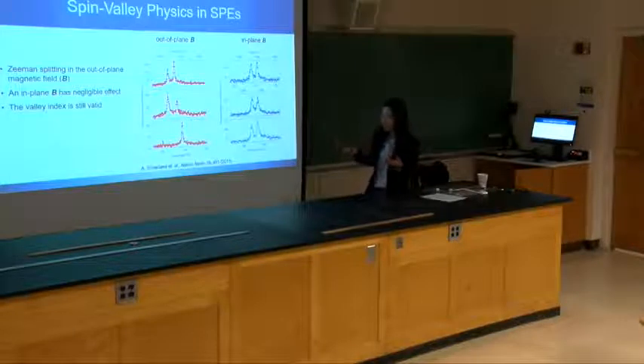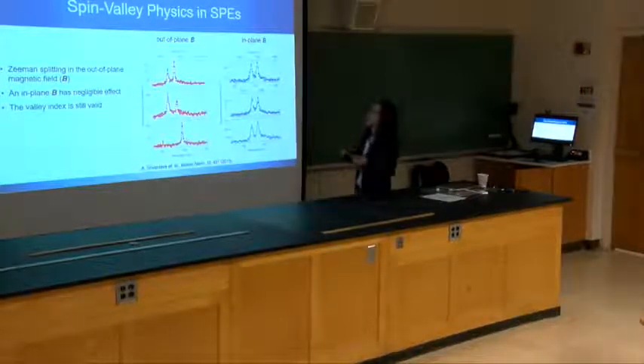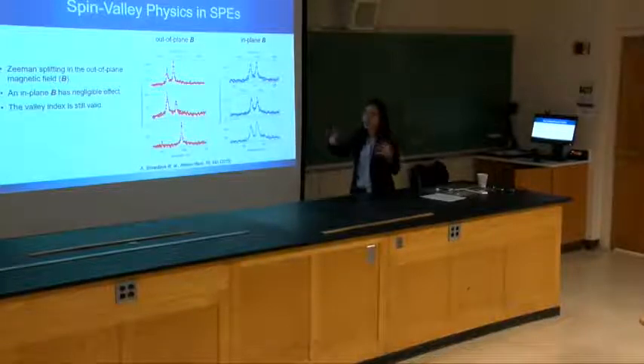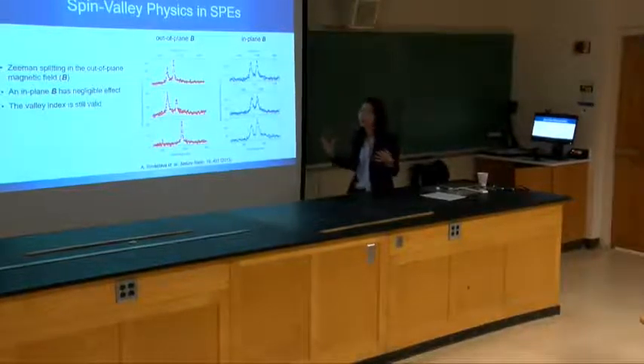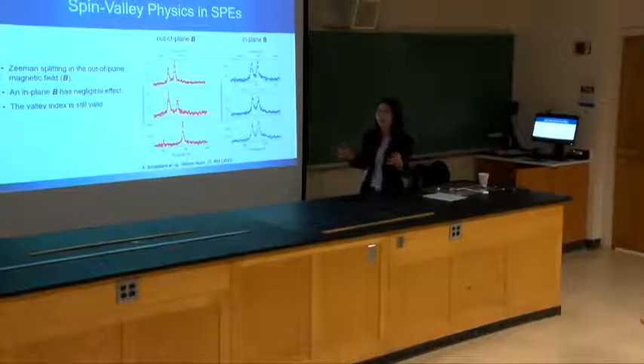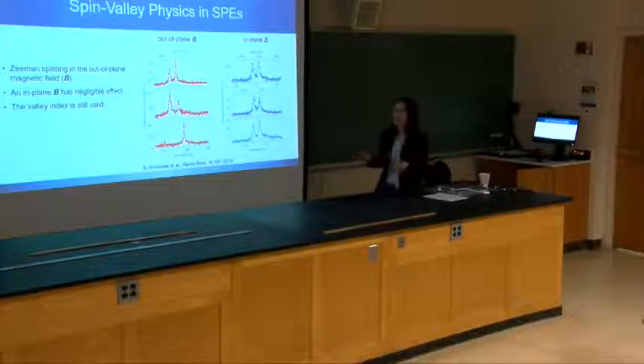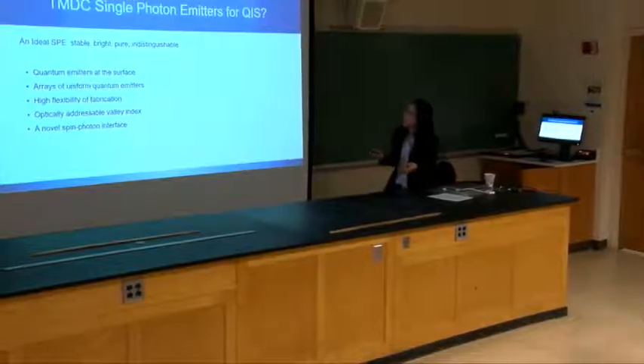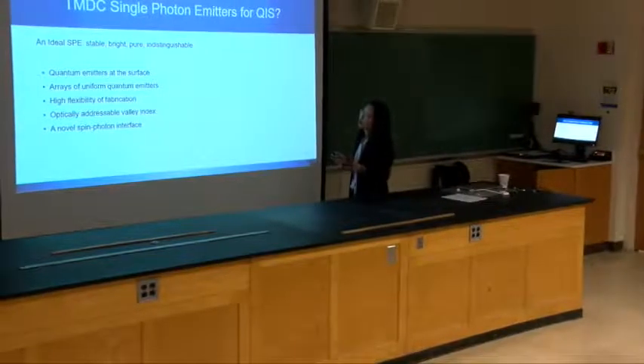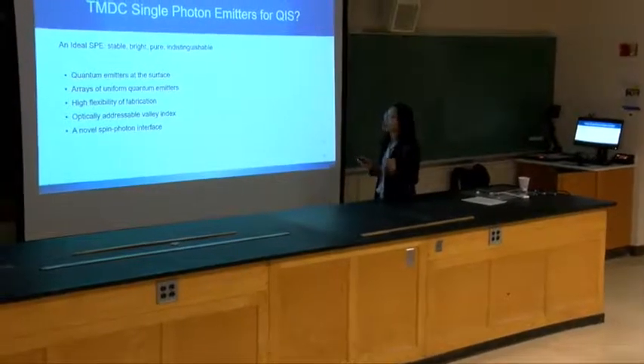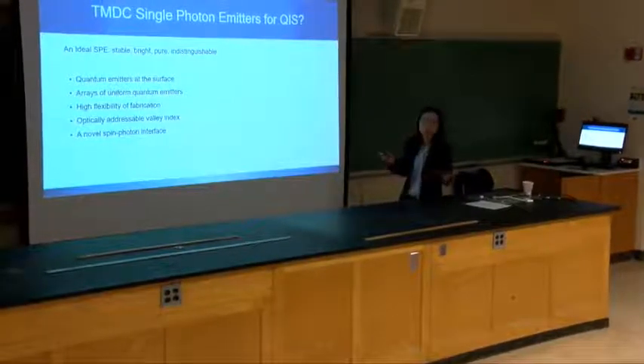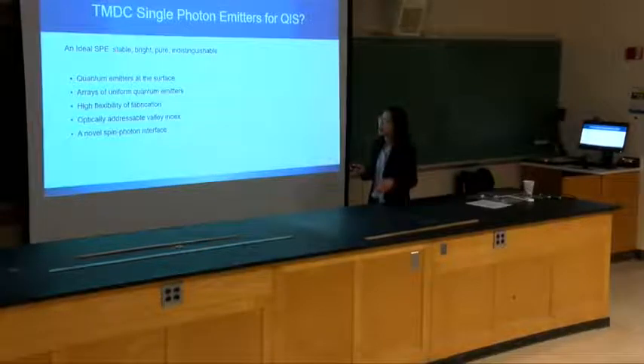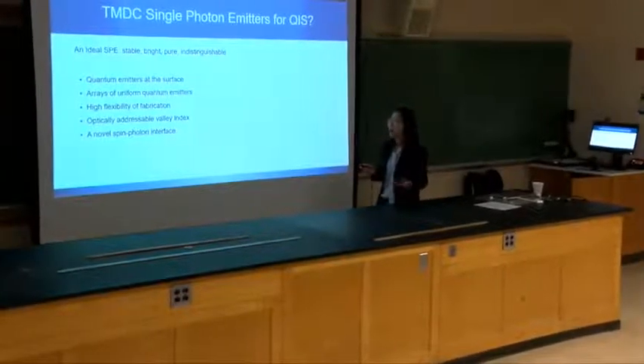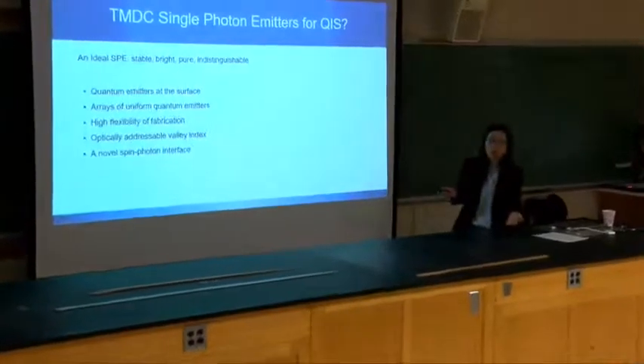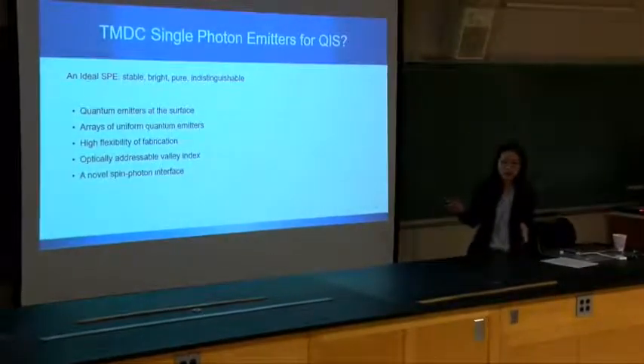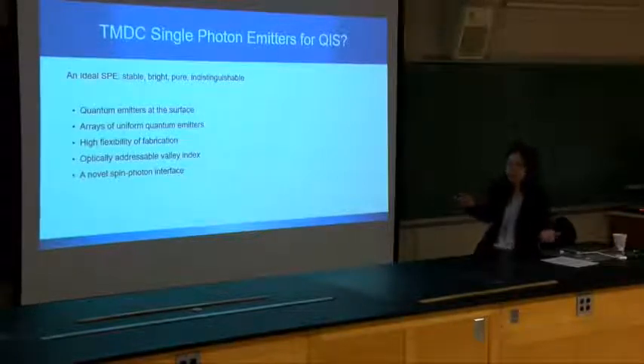That also means that the confinement length of this localized exciton is actually larger than the Bohr radius. Otherwise, it can't inherit the structure from the bulk. At this point, let's have a brief summary of TMDC single photon emitters to see what we can use for quantum information science. Ideally, a single photon emitter has to be stable, bright, pure, and indistinguishable. But I have to say that even the well-developed or very mature systems are not perfect. Nothing is perfect so far.